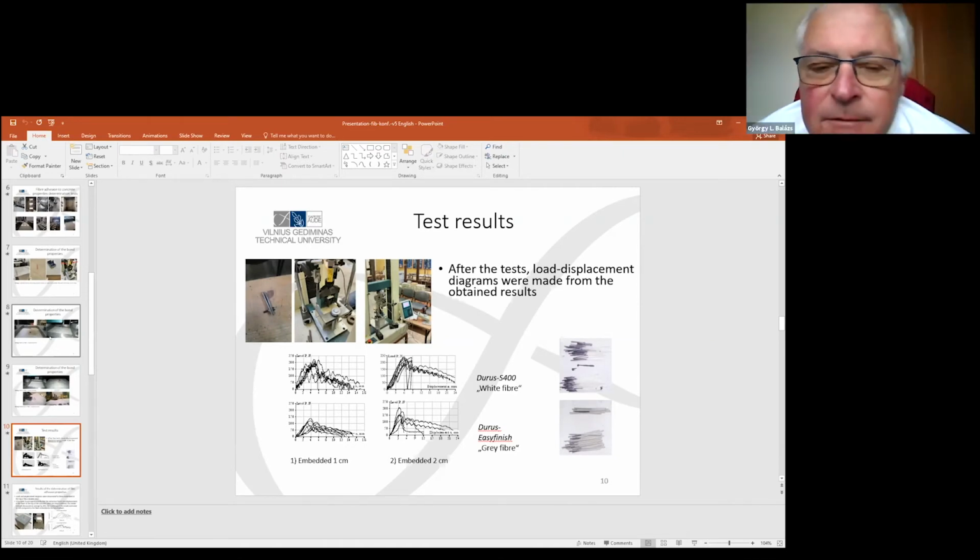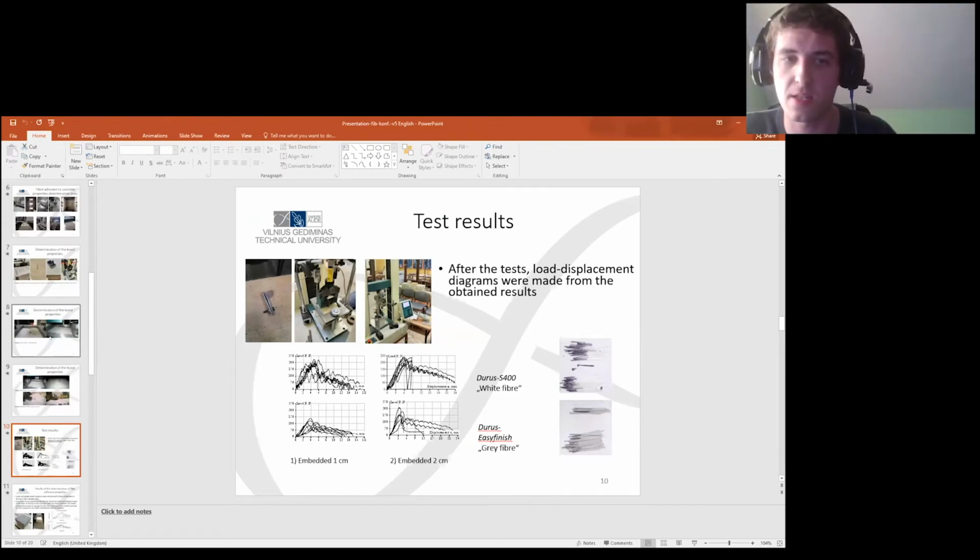Not necessarily a mistake. The mechanism of how we fasten these things, it's very easy to damage the fiber itself. So if you would fasten it a little bit too hard or a little bit too easy, it would either slip out of the apparatus or it would get damaged a bit, and then these diagrams would differ.